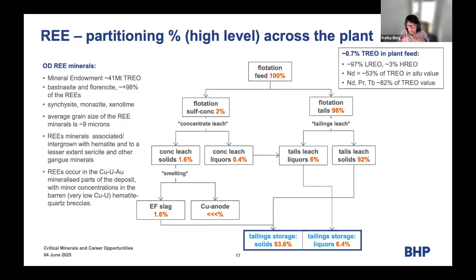And you say, well, that's interesting. We won't worry about that cons leach feed in. It's important to understand that, yes, our current tailings leach circuit is extracting a little bit of rare earths. It's not rare earths from the rare earth minerals. It's the rare earths that are contained in the uranium minerals that we're dissolving. So we do have a little bit in there, not a lot, but we know it's there and we know why it's there. And we have considered options to put a plant in to strip that material out.